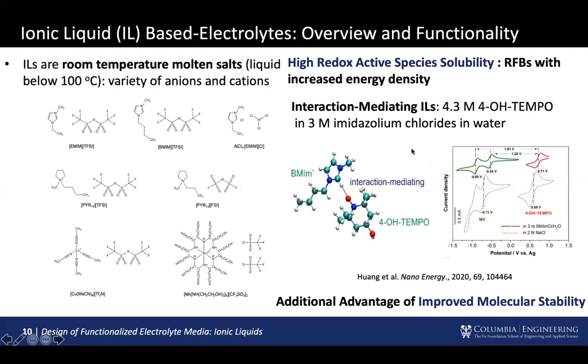So that again translates to a higher energy density battery. And an additional advantage here is that by binding to the organic species, the ionic liquid was able to improve the molecular stability of this compound over many cycles. Again, a challenge that we talked about for the organics. So we kind of see that these ionic structures that bind species have a dual function of increasing their solubility and also improving the stability of these redox active molecules.